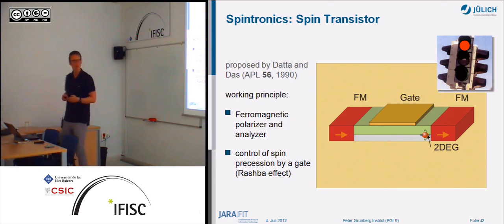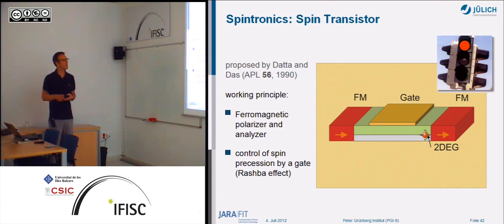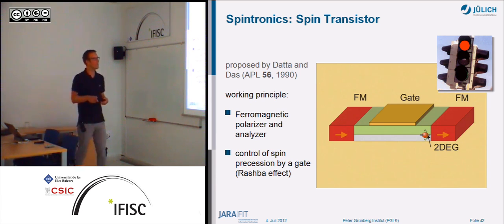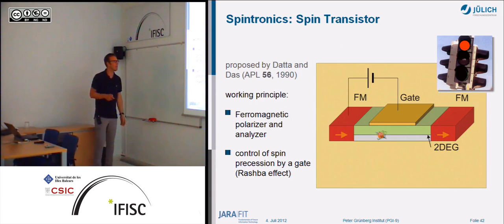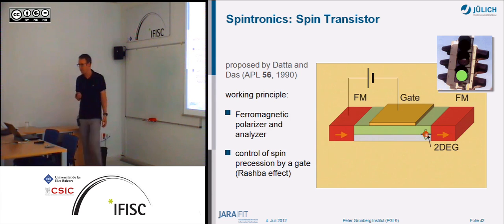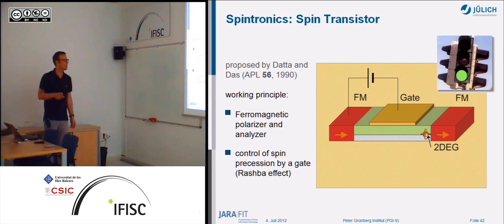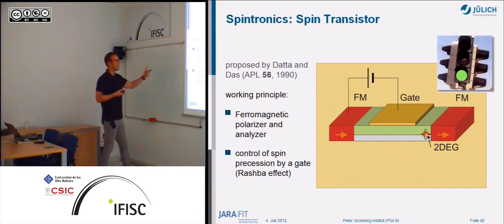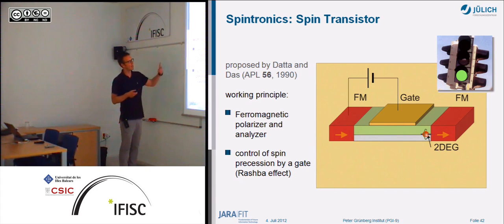And this is because of spin-orbit coupling, mainly Rashba spin-orbit coupling. In this case, you see that it doesn't fit here, so the electrons have the opposite spin direction as the ferromagnetic contact, so it's a red light for the electrons here. And so if you switch on the gate, you can change the spin-orbit coupling, and in this case, the precession is faster, and then you have green light for the electron, so the electron can pass, you have a lower resistance. That's the main switching mechanism for the Datta-Das spin transistor.